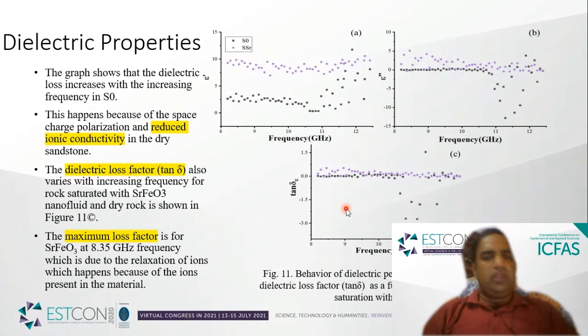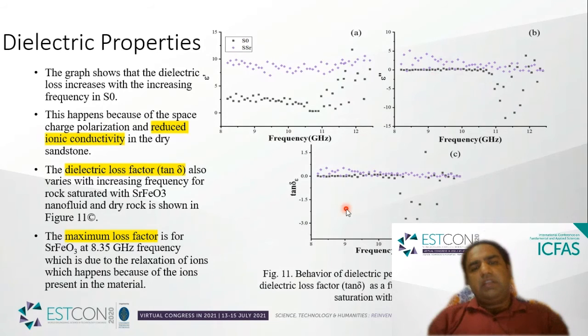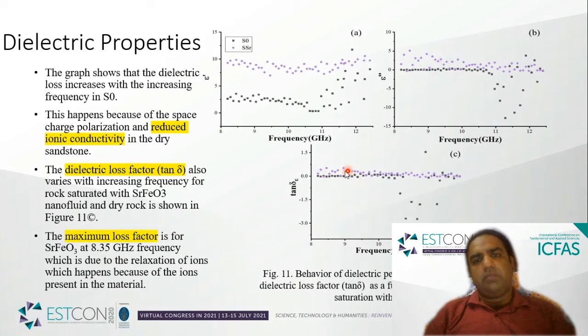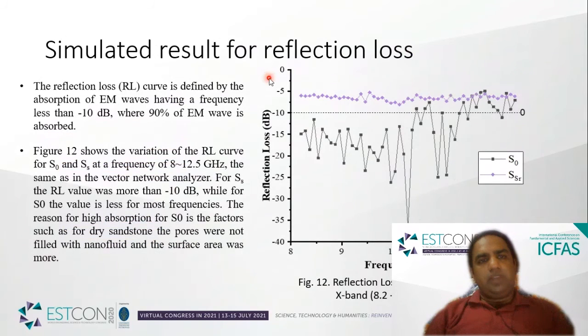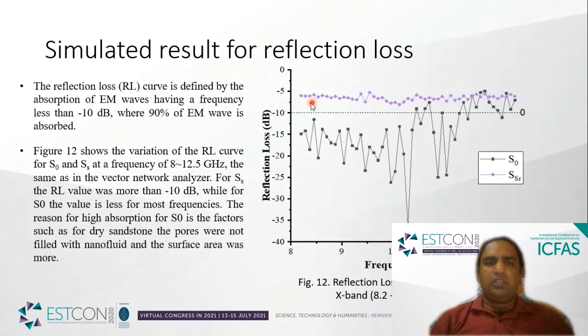And at the end, when we calculated the dielectric loss factor, tangent delta, we again get some high peak, or greater values, as compared to the dry sandstone at around 8.35 gigahertz frequency. So these results show that with the inclusion of the strontium ferrite nanoparticles, the dielectric properties of the material have been enhanced. Then we calculated the reflection loss parameters by simulation, which told us that the reflection loss for strontium ferrite is not very high. As we go down, the reflection loss increases, but in our case, the reflection loss for strontium ferrite is not very high.